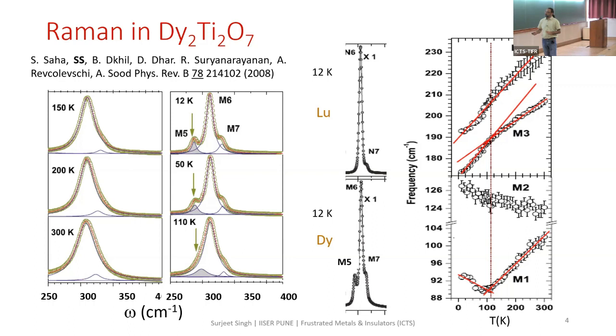So here's a small mode which is sitting here. What you do is you start lowering the temperature. As you lower the temperature, nothing really happens down to about 150 Kelvin. But as you cool below 110 Kelvin, a new mode appears around this 280 wave number. And when the sample is cooled down further, this mode becomes more and more pronounced.